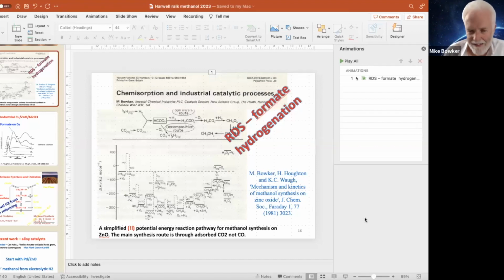This began experimentally, obviously, and academically in trying to understand alloying and its effect on methanol synthesis. We were very surprised first when we found that palladium alloyed with zinc. We were also happily surprised to find that that was a very selective kind of material. So that came as a big surprise to us. Now, although the loadings are much lower than in a copper catalyst, here we typically use 5% palladium, but we can use as low as 1% palladium. That is still a very expensive system to make commercially.